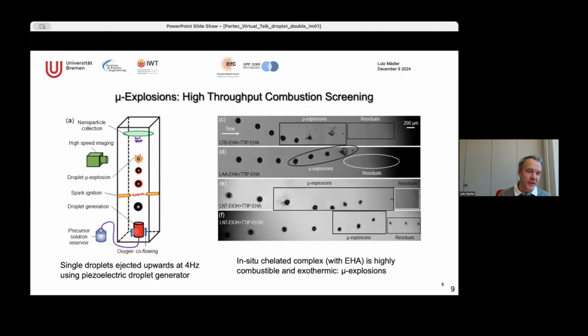We go up, down. We have those droplets here. We ignite them here. We let them burn, and at some point they react. And in most of the cases, they form a micro explosion. And you can see that here. So this is 200 microns. These droplets are below 100 microns. They fly, and at some point they get into micro explosions.